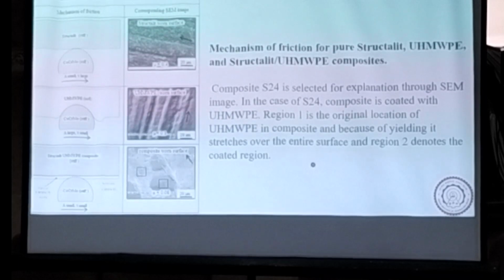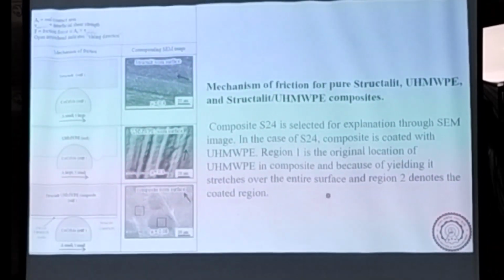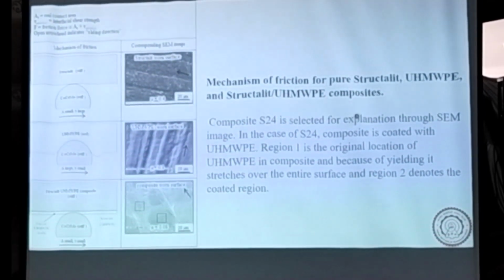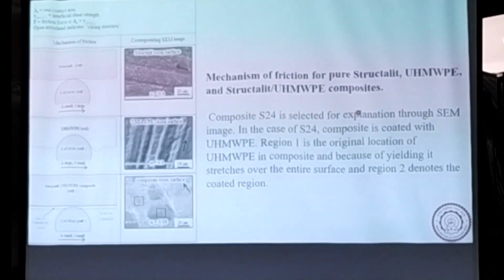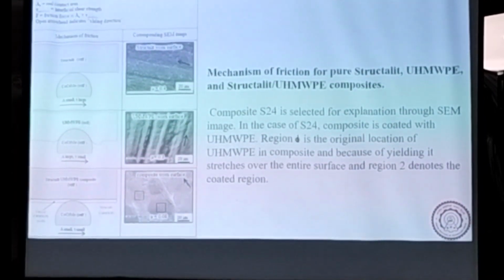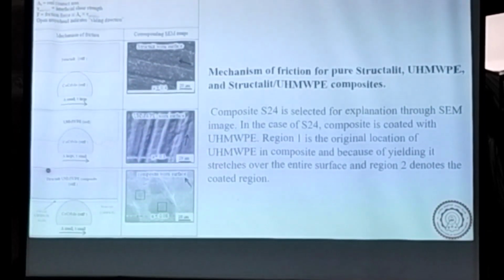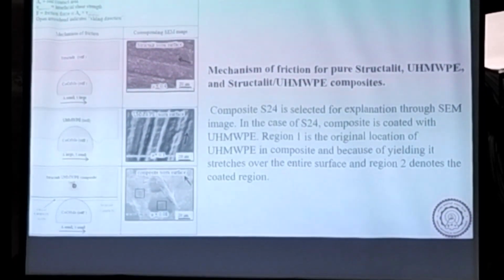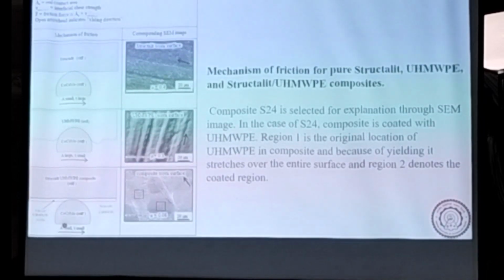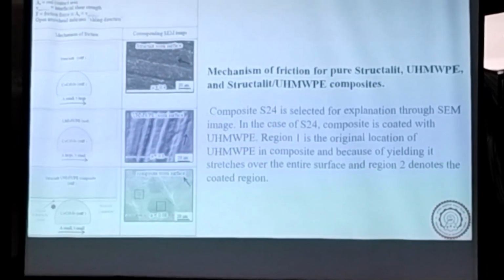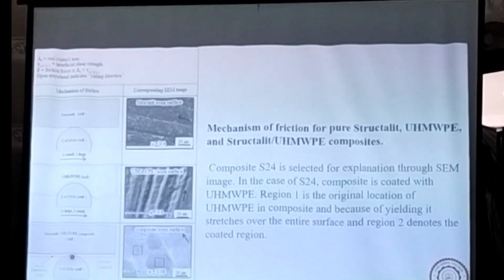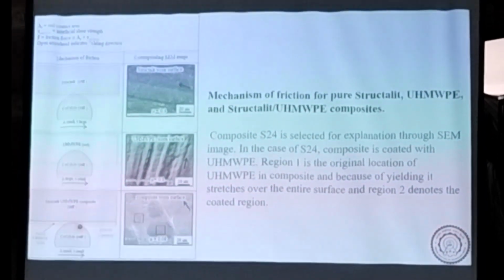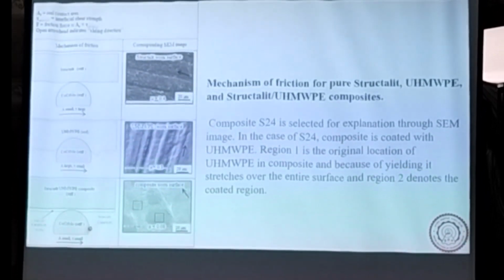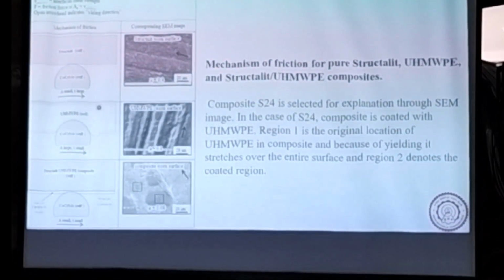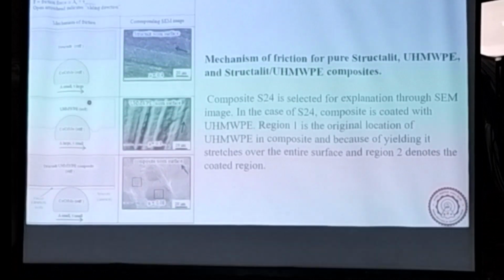very well covered. So we thought about the mechanism of friction, why friction is less for the composite compared to UHMWPE itself. Basically we understood that if you have two stiff or high strength materials sliding against each other, and there is a thin layer of lubricant, a low shearing material, in between, then this condition gives us a low coefficient of friction compared to a situation where you have stiff and soft material.